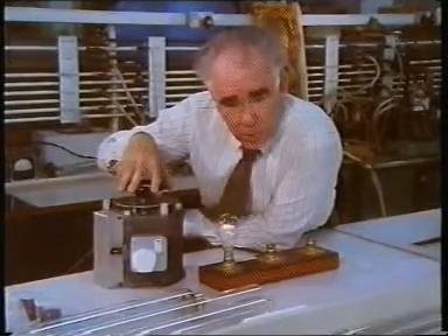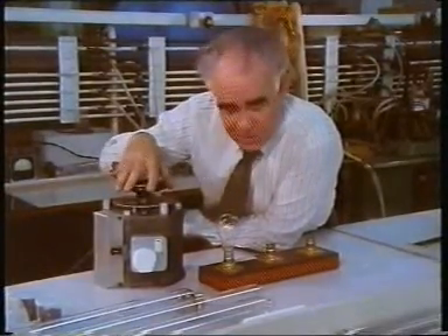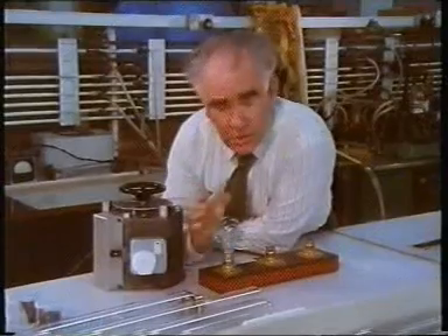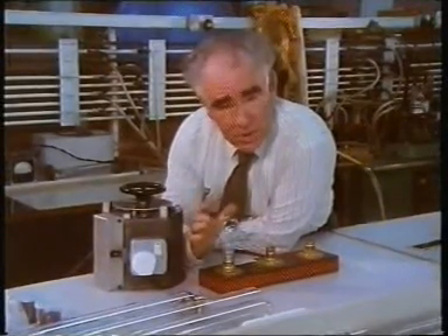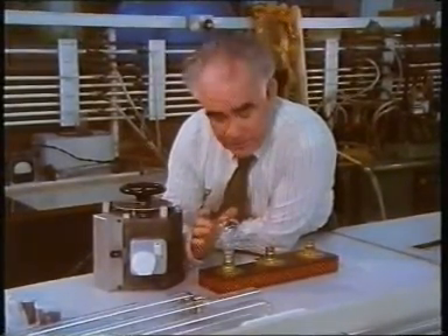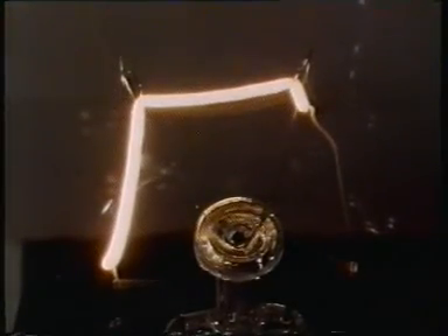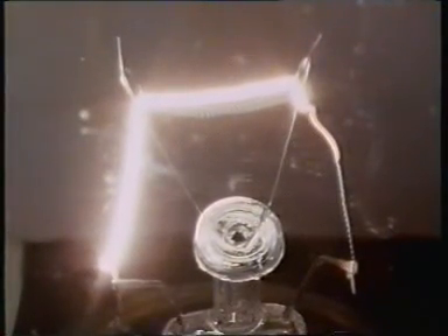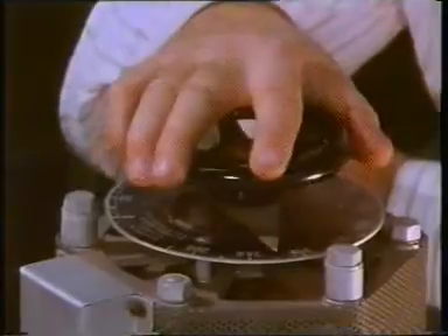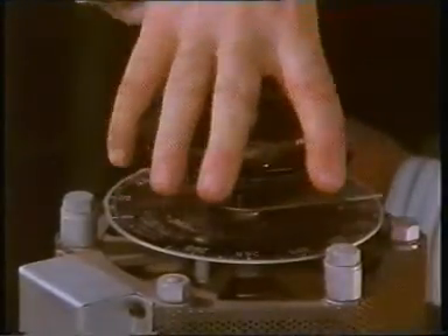Well, GLS bulbs are usually filled with a protective gas to reduce the volatilization of the tungsten. But it has a snag. It has a cooling effect. The sheath of gas is smaller over the single coil than it is over the single strand, and it's smaller still over the coiled coil. The coolant gas is taking more heat away from the single strand, which is consequently unable to reach the same temperature and emit as much light as the coiled coil, even though the same current is flowing.